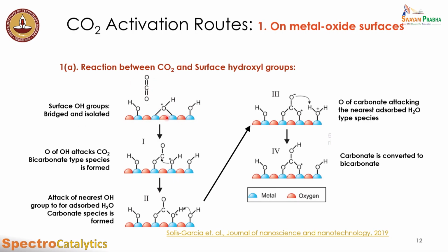So what happens when CO2 comes near this kind of OH group? The CO2 first gets a bent configuration where one oxygen is connected to the metal atom due to electronic transition, forming a ligand between the metal and oxygen. Then there is an nucleophilic attack by the oxygen atom of the OH group, because this oxygen has a lone pair of electrons that can attack the carbon of the CO2, since the carbon is delta plus charged and the oxygens are delta minus charged. That electron attacks the carbon, forming a carbonate species - specifically a bidentate carbonate, anchored to the surface on two sides.